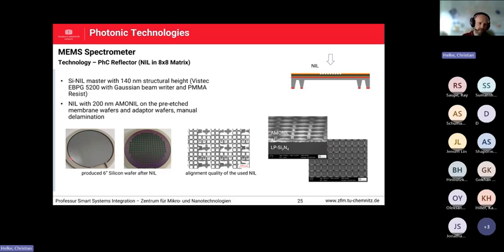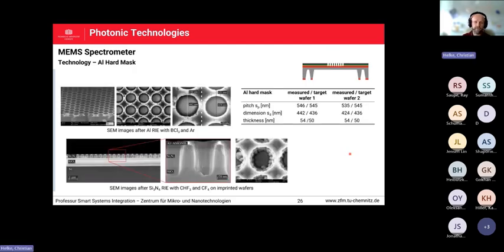You see here the front side, this matrix of, I guess it was 8 by 8, of these imprinted nano patterns. Looks really nice. And the pattern transfer in the photoresist layer, if you see it, for example, here in this SEM image view, it looks quite well. You have all of these nice structures of the photoresist, it's the AMONIL resist, on the aluminum on the silicon nitride layer itself. Afterwards, everything will be etched.